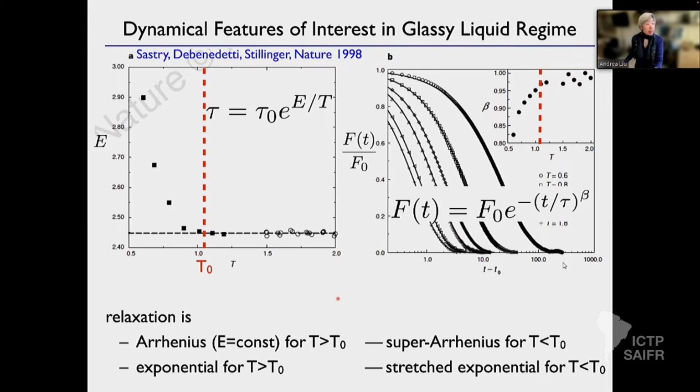In the experiments, you see super Arrhenius behavior whether you fix the volume or the pressure. But there is a very strong volume dependence. It's very strongly density dependent. And so as you increase the density, the barriers get higher very rapidly. That's because it's the hard cores of the particles, right? You're getting into that 1/r to the 12th part of the potential. It's very, very steep. It's those repulsions that are very strong. And so that's seen experimentally.